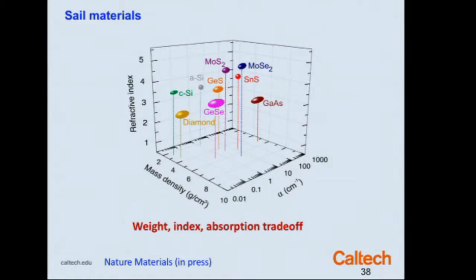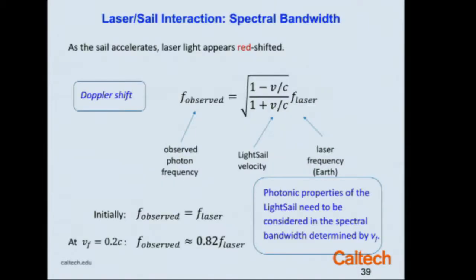And in thinking about materials, we want materials that have very, very low absorption coefficient, and this is absorption expressed in inverse centimeters, mass density, which of course is as low as possible in grams per cubic centimeter, and high refractive index, because it's easier to make dielectric optics and highly reflective materials with high refractive index. So these are materials that pop out as interesting materials. So crystalline silicon is a good material. Diamond is a good material. Some of the chalcogenides, tin sulfide, molybdenum disulfide, molybdenum diselenide, may be all interesting materials to use.